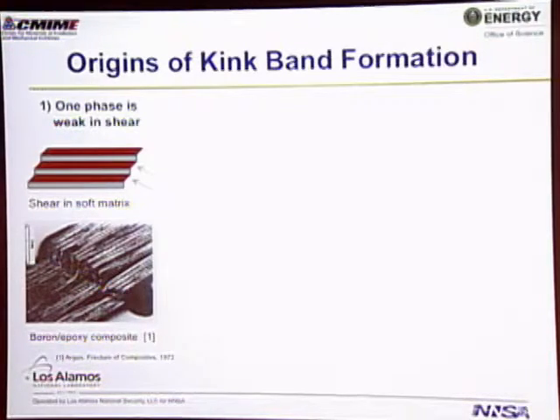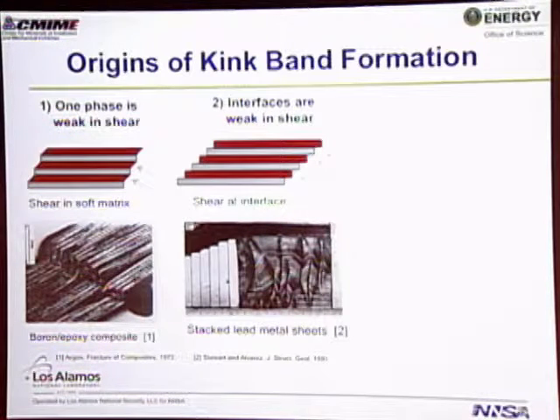This is going to become important when we start talking about shock and how this material would behave under an armored kind of application. So if we think about how these kink bands form, this is like a classic physics problem, actually. It's been studied by physicists, geologists, and so forth. One approach is looking at boron epoxy composites, so like a very stiff fiber inside an epoxy matrix. And you can also get kink bands forming in those. That's usually associated with a fracture of those fibers. You can also test these.